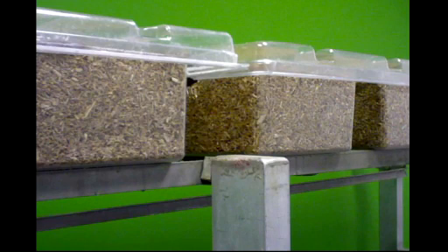We put it in our factory at room temperature. It sits in the dark, no light, no watering, no energy input needed. And in about 3 days, it self-assembles. So I'm going to press go. And if you can see this well enough, you'll see it turn white. If you can't see it, you can go to our website and check out a video there.